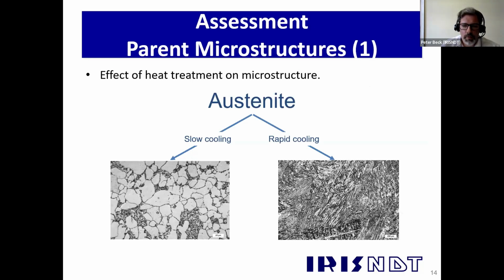So I don't know how much everyone knows about metallurgy, so I'll just give a little bit of background on that. So typically we're starting off with something heated up into the austenite range. And then if we go through a slow cooling process, then if you're familiar with the carbon iron diagram, you'll get something like the left-hand side. So you'll get a two-phase microstructure for a steel, comprising the light-coloured grains, which are ferrite, and the dark-coloured grains, which typically would be pearlite. To be honest, in this image, they're probably more like bainite, which is somewhere between slow and rapid cooling. But still, you've got that quite distinct two-phase microstructure.